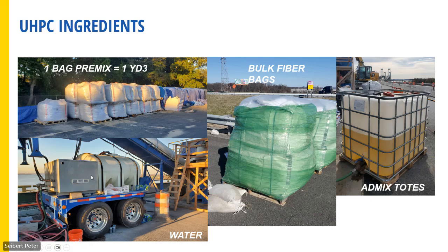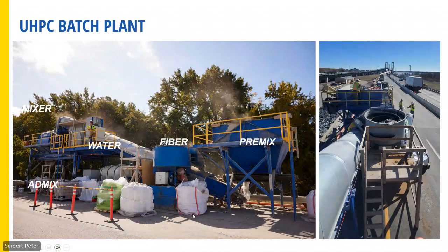We've got water and admixture that all goes into the mix, and that was handled right on site in the batch plant. This batch plant was designed in conjunction with a company out west called Mixer Systems. They have a lot of these high shear mixers for different concrete mixing applications, and they've been pretty prevalent in the UHPC mixing industry. So we went to them. We designed something that specifically could be used in a single lane closure so that we could leave 3 lanes open for the DRBA at all times. 1 lane for the mixing operation, 1 lane to transport our buggies and dumpers past. You can kind of see in that picture on the right. The material would be transported up past the batch plant there, and any other construction operations could access through the work site without needing an additional lane closed, which was really important for us.